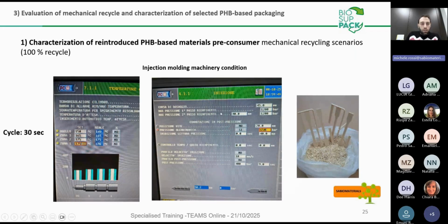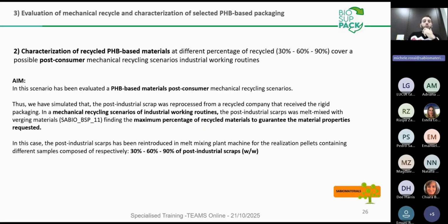Here, more or less, you can see the settings used to obtain the specimens: a total cycle time of 30 seconds. The temperature setting is 117 in zones 1 and 2, where the material is typically melted and compressed in the third part of the screw of the injection molding, and the nozzle at 150. Also in that case, we found that the inverse temperature profile represents a good solution to obtain the specimens. In this second picture, some parameters of pressure, speed of the extruder, speed of injection, and post pressure permit to guarantee obtaining compact specimens without bubbles inside, to avoid problems during the characterization.